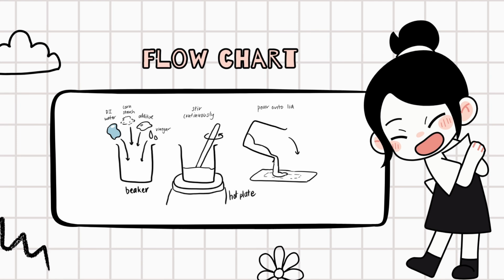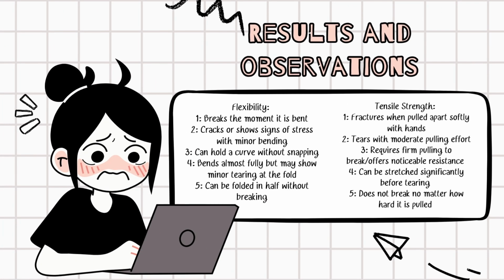5 trials were conducted, 2 on glycerol only, 2 on glycerol and PVA, and 1 on glycerol and sugar. The variables kept controlled were the proportions of ingredients added to the beaker, the heat time, the heat level, and drying conditions. The flexibility and tensile strength of each bioplastic was tested qualitatively by bending and pulling each sample by hand, with my results recorded on a 1 to 5 scale as outlined here.